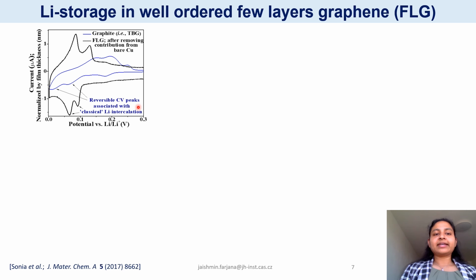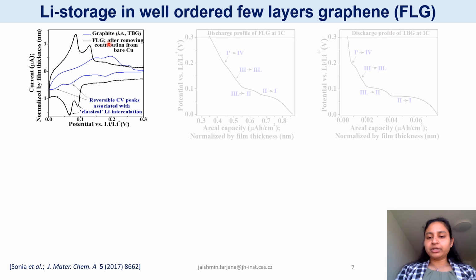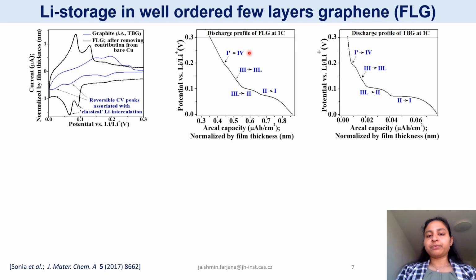Then we tried to test it against lithium, and we compared its performance with graphite, and we could see that the cyclic voltammetry and also the potential profile of galvanostatic charge discharge are quite similar for the few-layer graphene and graphite. This indicates that if our few-layer graphene has very few defects and is very well ordered, then even for this reduced dimensional scale, we could have a classical lithium intercalation similar to that of the graphite.